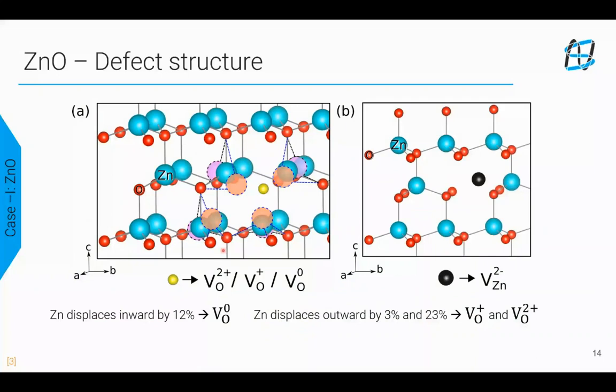Now, these pristine unit cells don't necessarily need to have extrinsic defects, but intrinsic ones are inevitable when you grow these, either if you deposit them or you're growing them or you find them naturally, as you had seen from quartz and other crystals which are naturally formed, tourmaline and emerald, you have several inevitable intrinsic and extrinsic defects. So in ZnO, the kinds of defects that you would also see are oxygen vacancies, wherein the lack of oxygen is called the oxygen vacancy, and sometimes the lack of a zinc atom site, which is called the zinc vacancy. Due to this, there are several changes in the optical and electronic properties because of these vacancies. When oxygen has a vacancy, there is a distortion in the local crystalline structure.